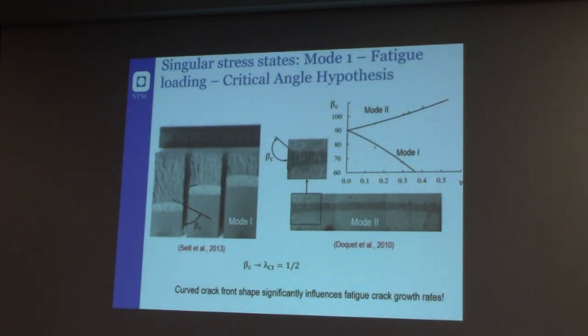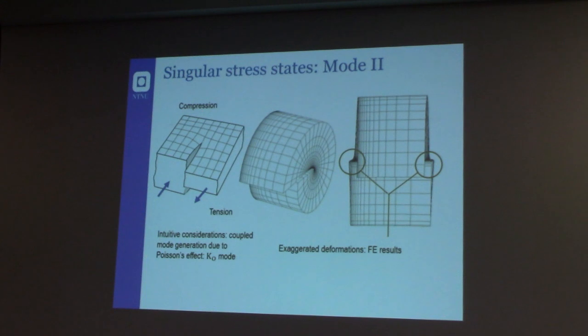But what is very interesting is what is happening if you consider the mode 2 stress field, which is the most interesting part. Actually, what we did was to apply a kind of nominal shear stress to our component, and due to the three-dimensional effect of the finite thickness, what you can find locally is that you can see also an out-of-plane displacement in this direction. Actually, you are applying mode 2, but what is happening is not only mode 2, which is this configuration, but due to the thickness or Poisson's effect, you are pushing in one direction and you are putting tensile in the other direction.